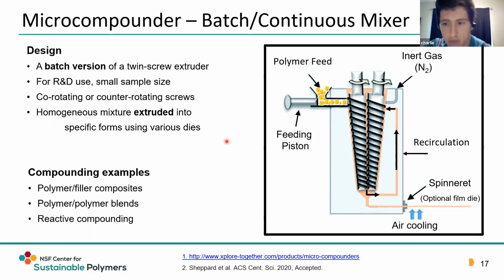Usually for R&D use. If you look over here on this right figure, we have the polymer feed, conical twin screws for mixing, a recirculation chamber, which is to ensure proper mixing. After your residence time is complete, you can then discharge the polymer out of the extruder, and then you can either produce films or a filament, depending on the die attachment you have. Typically, we produce filaments, but I will show you a die attachment in the future.